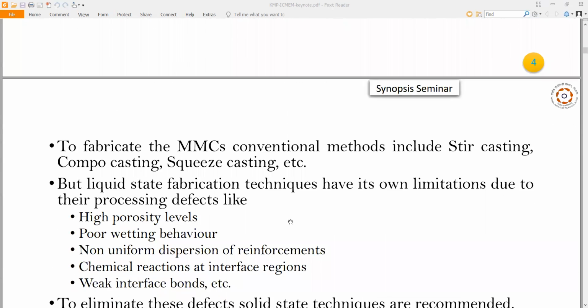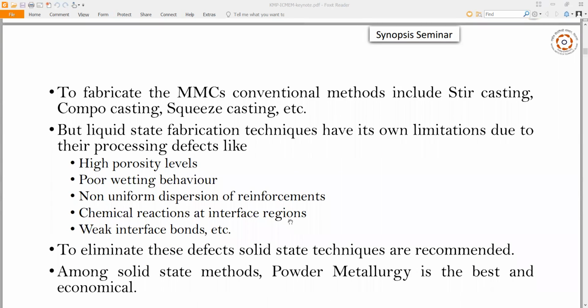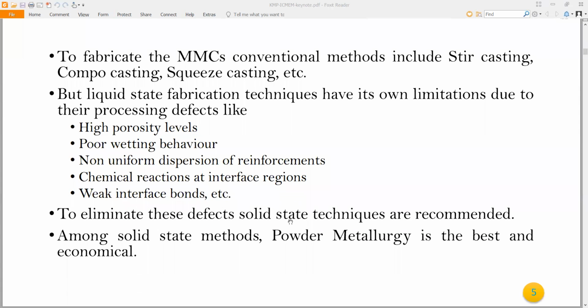Then, to fabricate MMC, that is metal matrix composites, conventional methods include stir casting, then compo casting, squeeze casting, etc. But liquid state fabrication techniques have their own limitations due to processing defects like high porosity levels, poor wetting behavior, non-uniform dispersion of reinforcements, chemical reactions at interface regions, then weak interface bonds, etc. To eliminate these defects, solid-state techniques are recommended, and among solid-state methods, powder metallurgy is the best and economical.